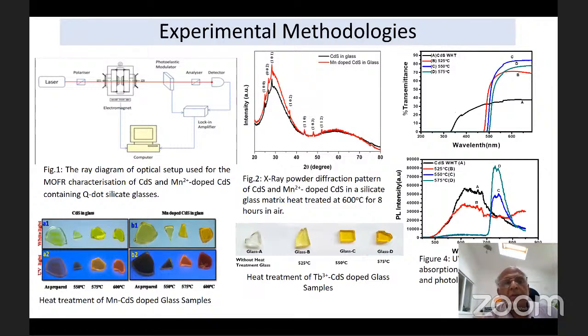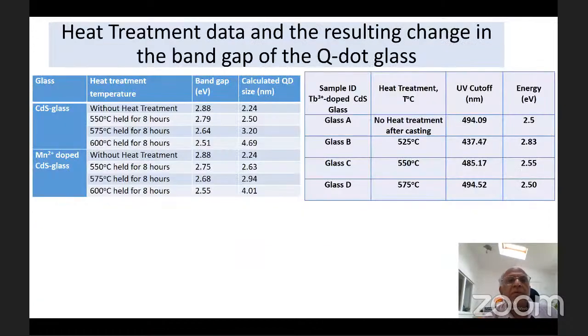By controlling the heat treatment, we can control the quantum dot size distribution, which we can also characterize by UV-visible near-infrared spectroscopy and photoluminescence characterization. In this slide, we can see the data for CdS glass, CdS and MnS doped silicate glass, and terbium doped silicate glasses. So you can see very clearly the band gap is dependent on the heat treatment condition, and from that band gap, using the Brus model, we can calculate the size distribution of quantum dots, and that gives us the average size, and the same technique was utilized for terbium doped CdS glass.